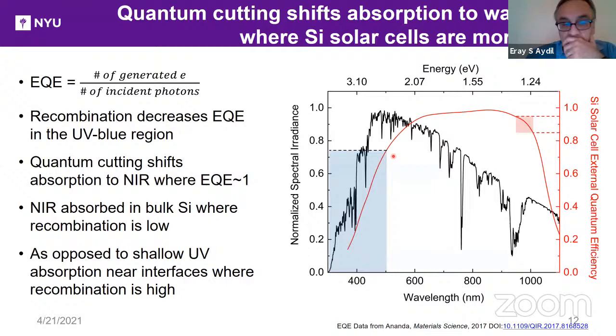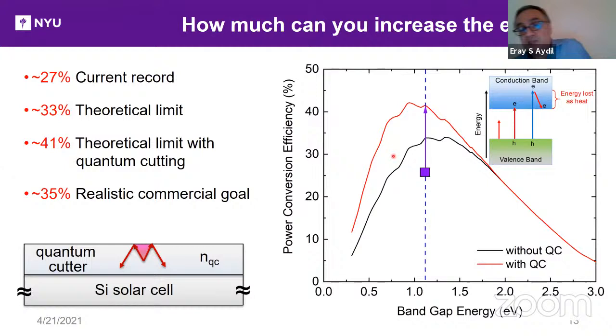So you might say, well, how much can you increase the efficiency with this method? Well, you can calculate it. You can repeat the calculation that Shockley and Queisser did back in the 1960s with quantum cutting. And so here is the Shockley-Queisser limit without quantum cutting in black. And here it is in red. And here is, in purple, the current efficiency, about 26% or so. So not only do we raise the limit from 33 to something like 41%,